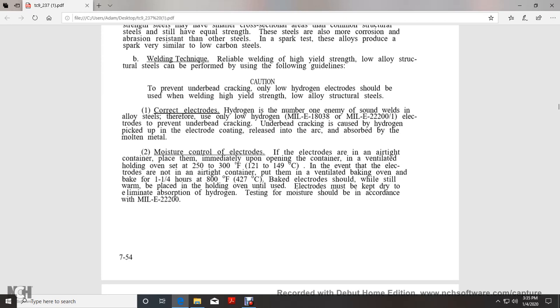Use caution to prevent underbead cracking. Only low hydrogen electrodes should be used when welding high yield strength, low alloy structural steel. Correct electrode: hydrogen is the number one enemy to sound welds on alloy steel. Therefore, use a low hydrogen electrode to prevent underbead cracking. Underbead cracking is caused by hydrogen picked up in the electrode coating, released in the arc, and absorbed in the molten metal. Moisture control of the electrode.